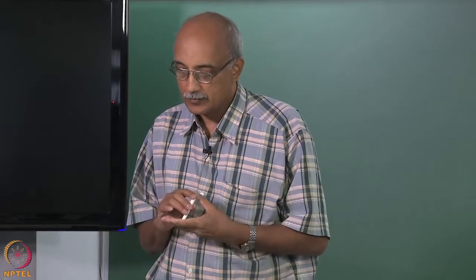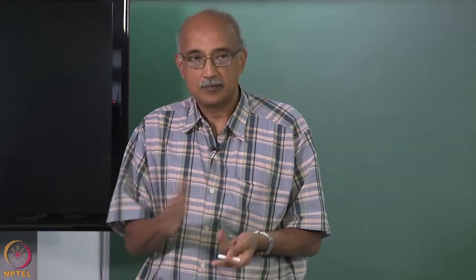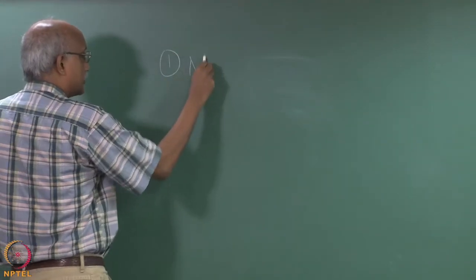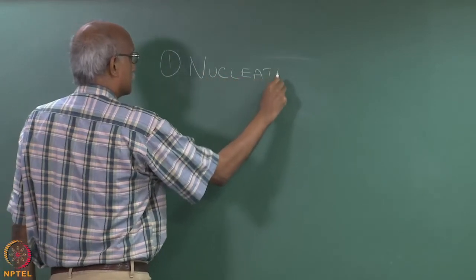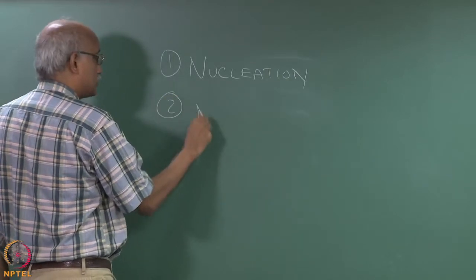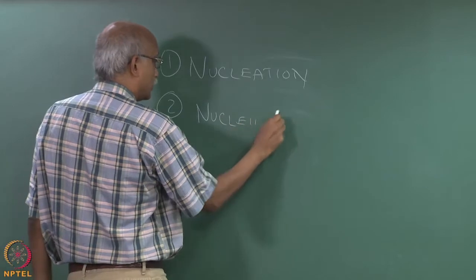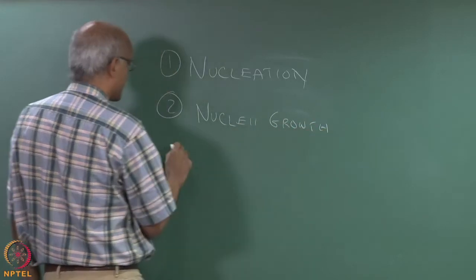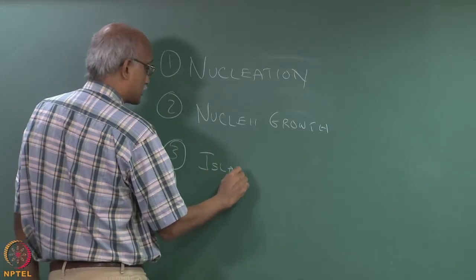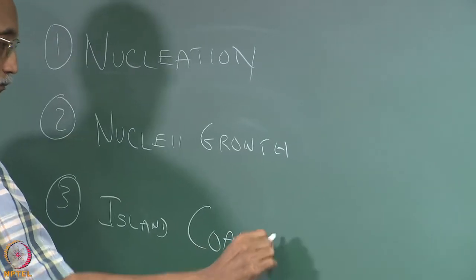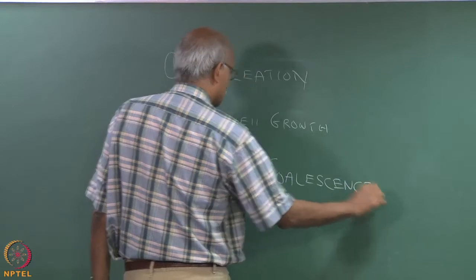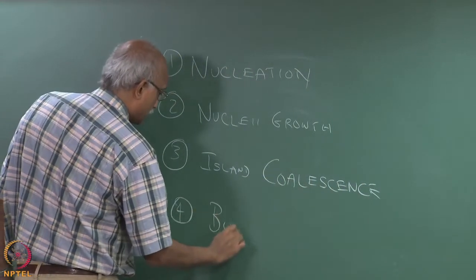The other aspect of CVD films that we need to be aware of is the actual sequence in which they form. When you deposit a CVD film on a surface, it doesn't immediately form as a smooth, continuous, uniform film. There are actually 4 stages in the formation of a CVD film. And these are, first you have a nucleation step. The second stage is called nuclei growth. The third stage is called island coalescence. And the fourth and final stage is where bulk film forms.